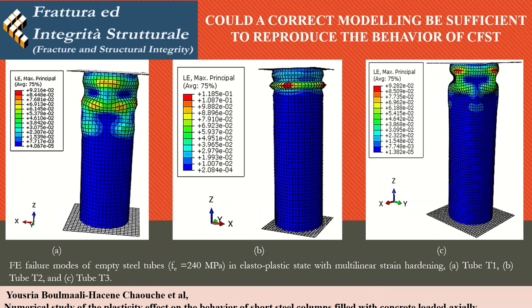We also notice a very good correlation between the experimental, theoretical, and numerical results, with sometimes a small difference not exceeding 10%. The numerical model with perfect elastoplastic behavior gives behavior very close to reality compared to the experimental tests.